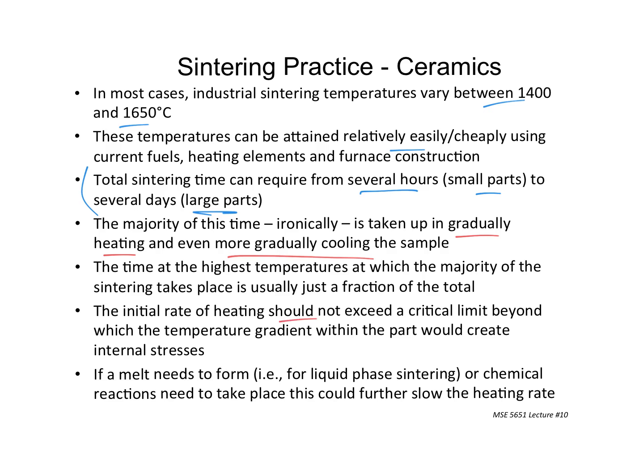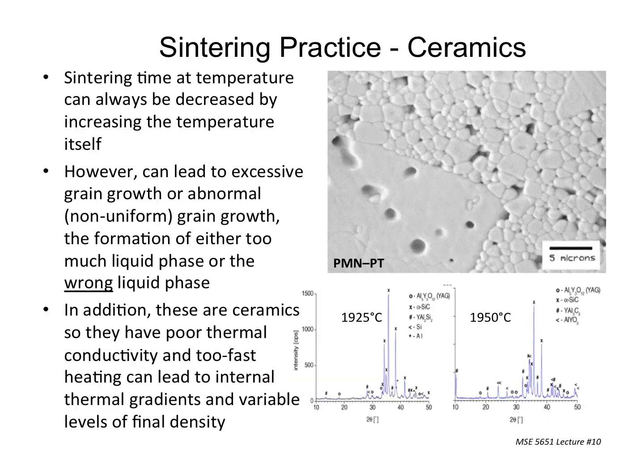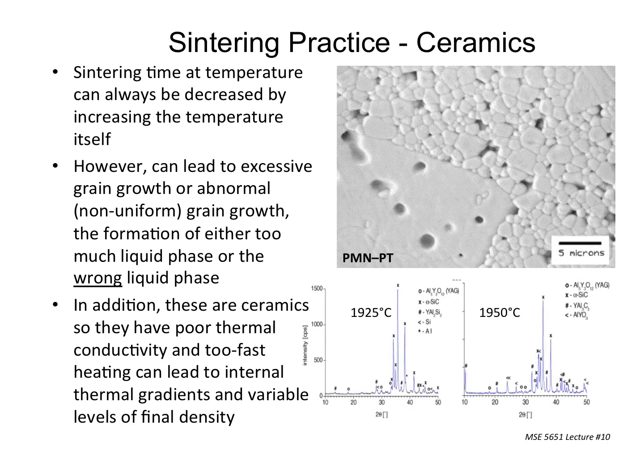The initial rate of heating should not exceed a critical limit. So we talk about fast firing, but even fast firing has limits. You don't want to create internal stresses. If the melt needs to form for liquid phase sintering, that takes time. It can be a chemical reaction that takes time to happen. And so all these things need to be considered.